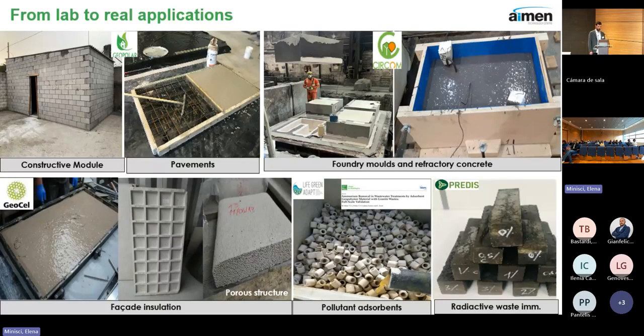And some of the applications that we have validated in our R&D projects, as I said, collaborating with our industrial partners in relevant environments. For example, in the Geopolar project, we developed some geopolymer bricks, and we built the small construction model that you can see in the image. In the same project, with a different material, we developed material for pavements. And in the Geofoam project, we developed a highly porous material that was obtained by the addition of a foaming agent. It was good for thermal applications.